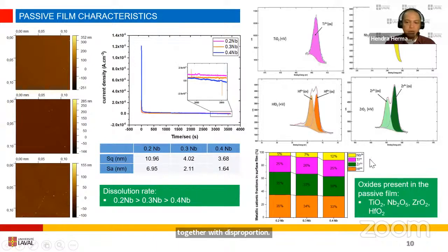Okay, and then we conclude that in the passive film we have this kind of oxide in detail. So it's not only the elements in the passive film, but we are also able to distinguish what kind of compound forms in the passive film, like TiO2, Nb2O5, ZrO2, and HfO2. So this is after we analyze the XPS curve. Okay,